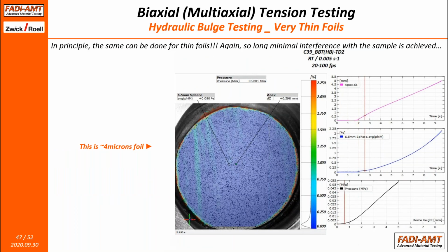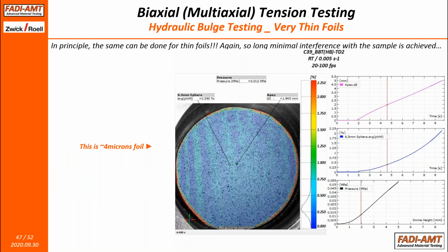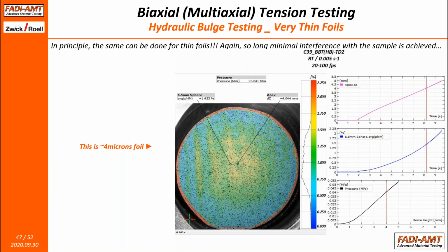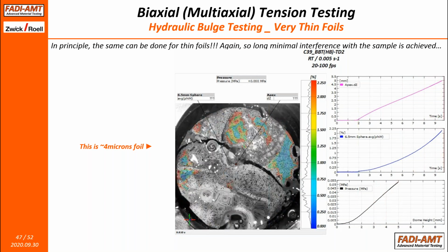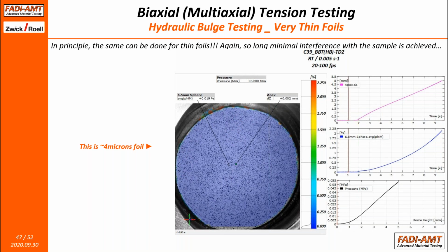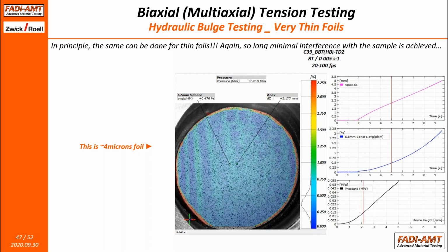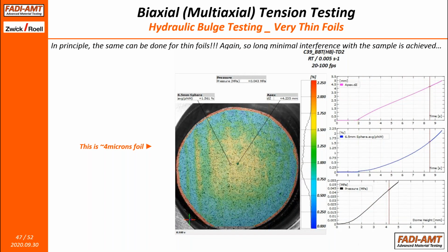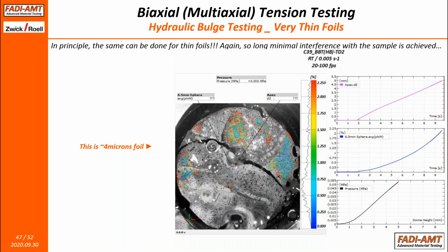One last example here is, what if you have to do bulge testing of thin foils like the ones that we showed earlier? This is a perfect example of how it can be done. Again, this is maybe an extreme of the bulge tests. This was done on a 4-micron foil, and we repeat the same exact rule. You can do it with any extensometer, whatever technique you use, so long as you minimize the interference and the influence on the sample itself.